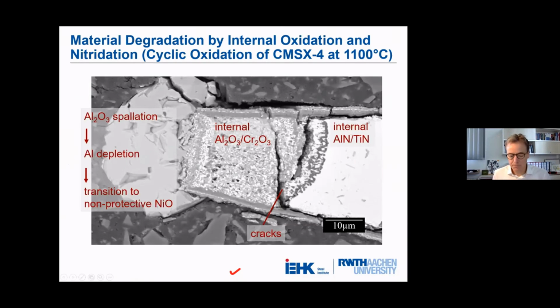If you have a closer look here, we see that thermal cycling causes repeated alumina spallation that ends up in near-surface aluminum depletion. This aluminum depletion causes a transition to non-protective nickel oxide formation, fast growing, as you can see. We call this a cauliflower, this fast growing nickel oxide, and then the internal oxidation and nitridation is combined with massive internal stresses and crack formation.